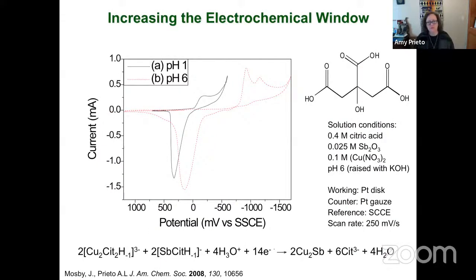And the first step was to figure out a way to electrodeposit this material directly out of solution. And remember that I told you we wanted aqueous solutions with, if possible, very safe chemistry. And so my very first graduate student, James Mosby, figured out how to do this using citric acid as a coordinating ligand. I'm showing you a cyclic voltammogram here in black at pH 1, which is the normal condition for dissolving antimony salts, very low pH.